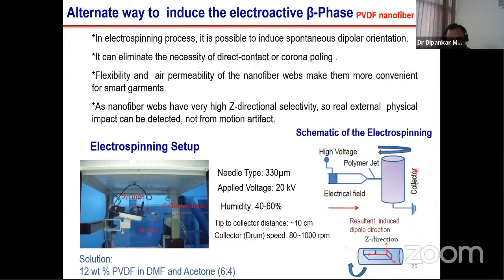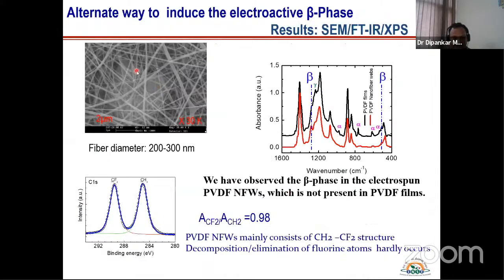And if we collect this polymer jet, then we can see it is a fiber-like structure. You see, this is the fiber-like structure. So that is basically spongy in nature, and one can integrate this with textile because it is air permeable in nature. And we did XPS spectroscopy.